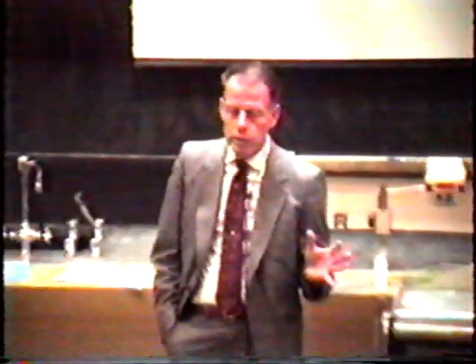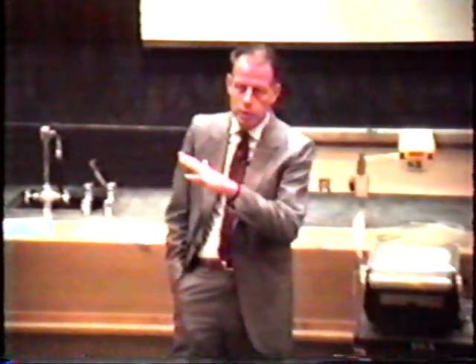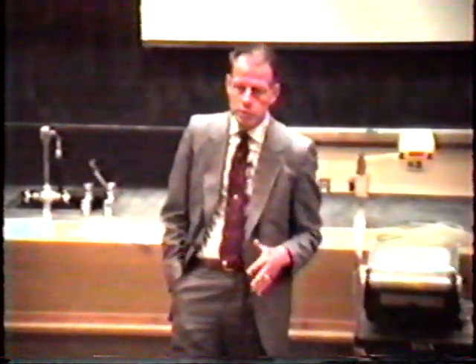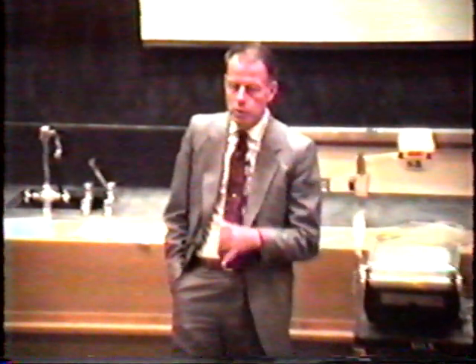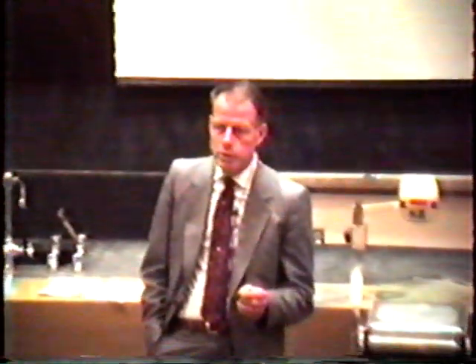Now, these are much smaller amounts than what Fleischmann-Pons have claimed in some of their experiments, but of course, we're working at much lower current densities. We cannot go up to the high current densities where they got their high power. They reported values up to 10 or 100 watts per cubic centimeter, but they had to go up to very high current densities. We're not able to do that with our power supply because it overloads, so we had to stay in the lower current regions, but where we're working correlates quite well with what they reported for the lower current densities, around 100 milliamps per square centimeter to 200 milliamps per square centimeter. But like you said, excess power, about 0.52 watts was the most that we saw.